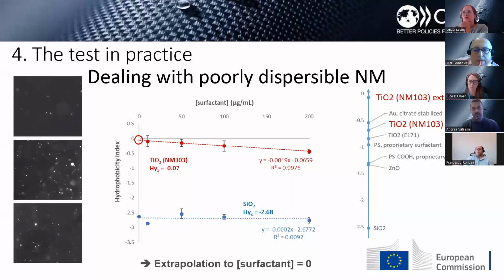To disperse these hydrophobic nanomaterials, we used a surfactant. Here you can see a graph showing the direct relation between the hydrophobicity index and the ratio of surfactant to nanoparticles. We used 4 different ratios, and we were able to extrapolate the value of the hydrophobicity index that the material without coating would have.